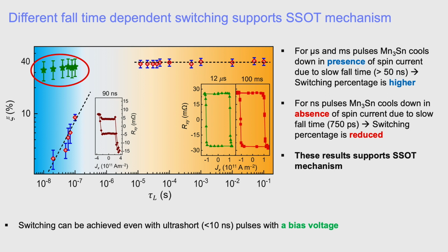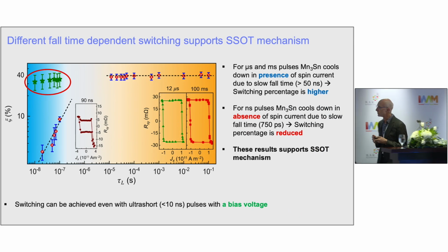And this is very interesting. It means we could use the same mechanism to switch very thick ferromagnetic films, which have a Curie temperature. We can tune the Curie temperature, the ordering temperature, so it's accessible with reasonable amounts of current. Then we could switch very thick layers, and that would be very useful technologically to create stable magnetic bits.